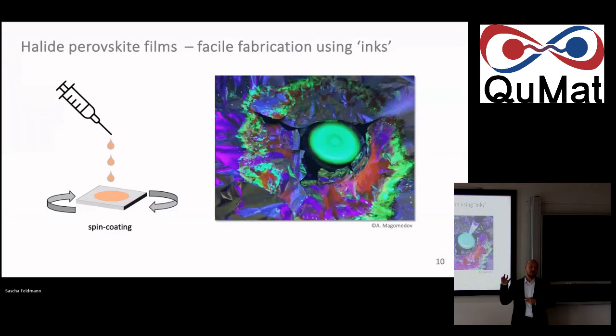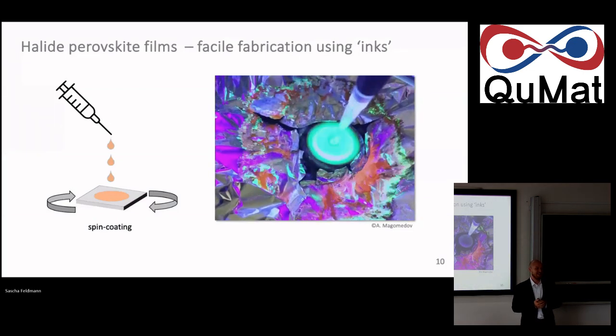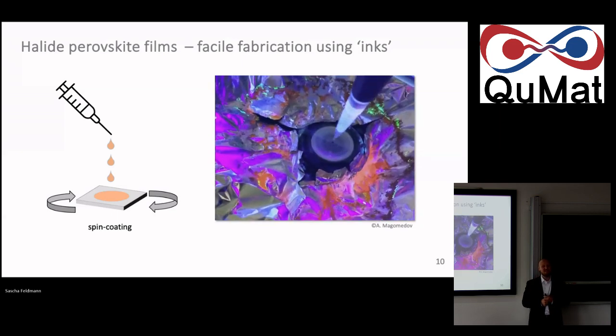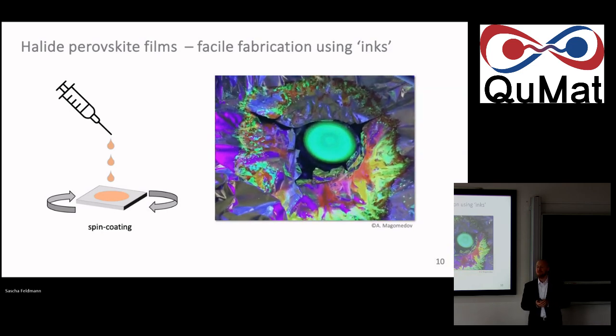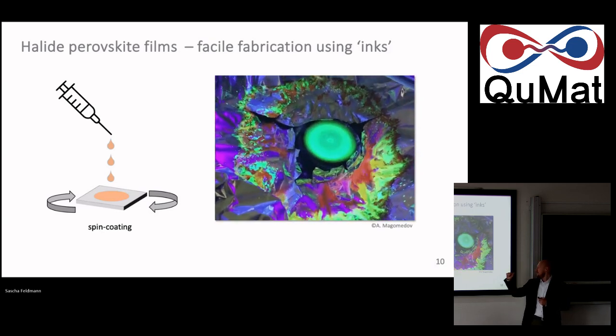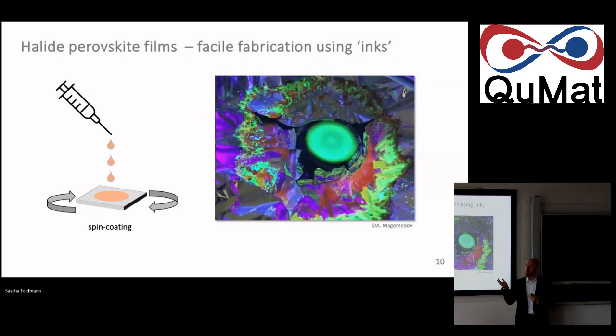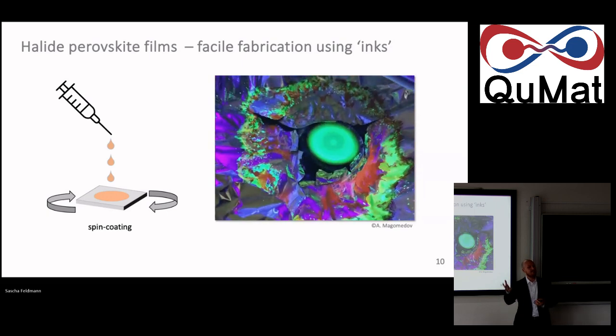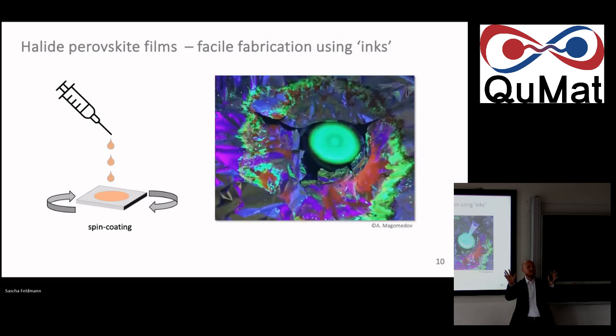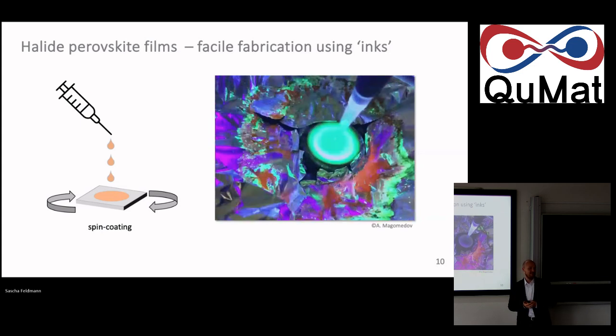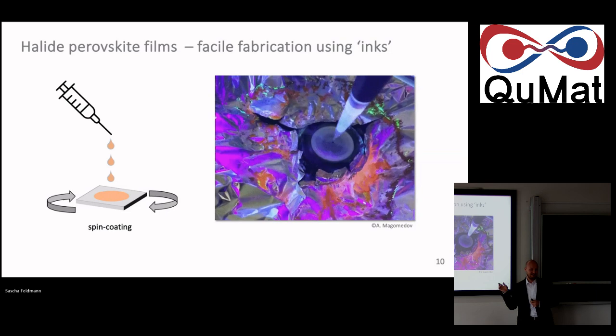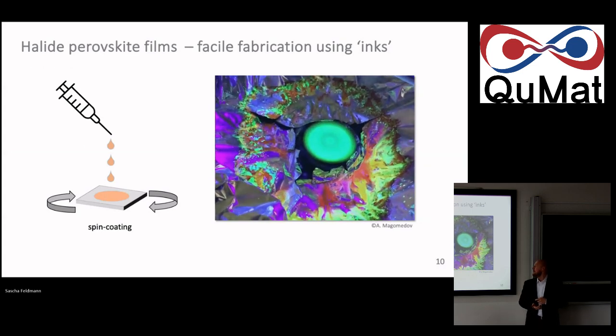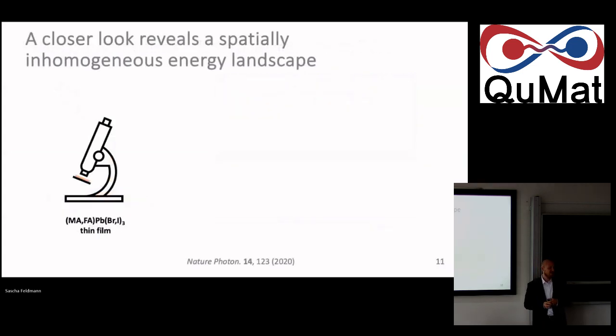So when I say it's very simple and easy to make these materials, I really mean very simple. You put a little droplet of your different ions on a spinning substrate. You heat the whole thing up to 100 degrees Celsius, something you could literally do in your kitchen, even though I advise against it because there are some toxic materials here. But you could. You shine a UV torch on this, and you see you've already made something remarkably fluorescent, something that absorbs those UV photons from your torch and shines them right back at you, so you don't seem to lose a lot of energy to heat or non-radiative losses. So this is really cool when we compare it to how we make a silicon wafer in the clean room. Still fascinating.